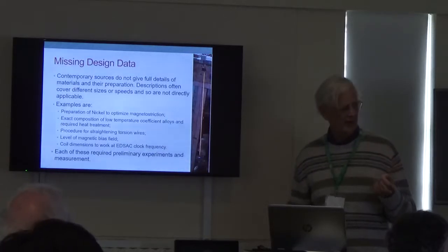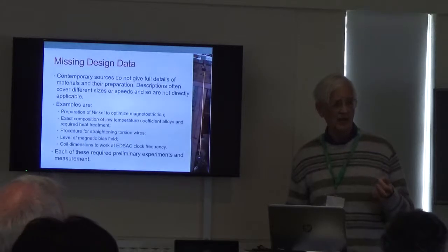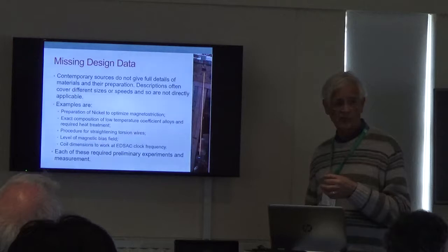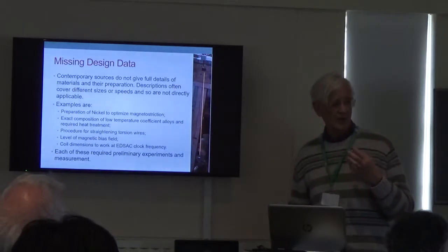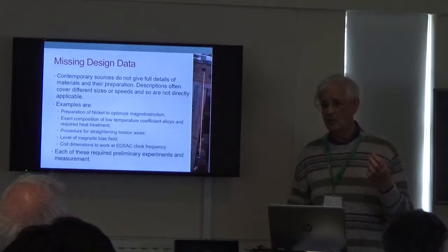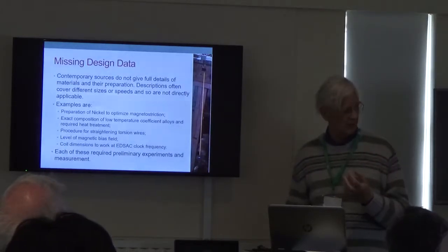So we did a lot of bench tests to experiment and find out what gave the best sensitivity and the best reliability. It turns out as you reduce the field strength, you get better sensitivity, but at a certain point you start getting hysteresis effects, so that the thing becomes unreliable because you've got inherent retained magnetism in the tapes.